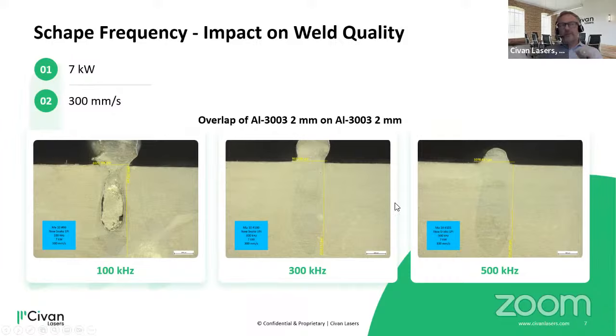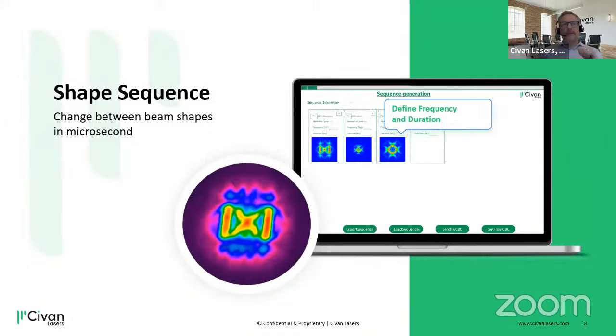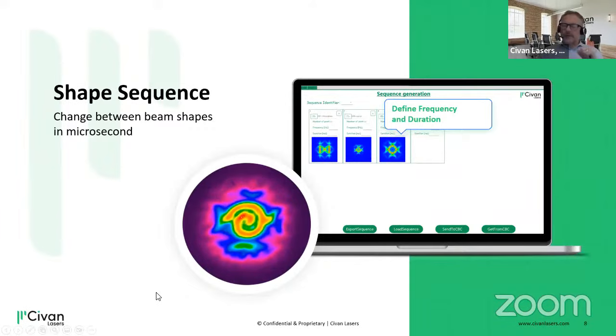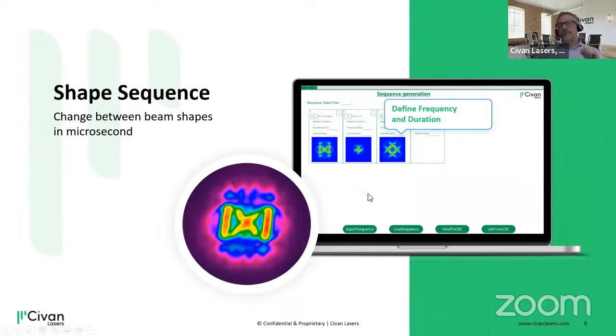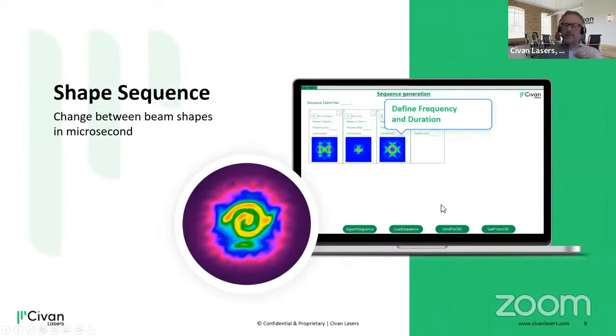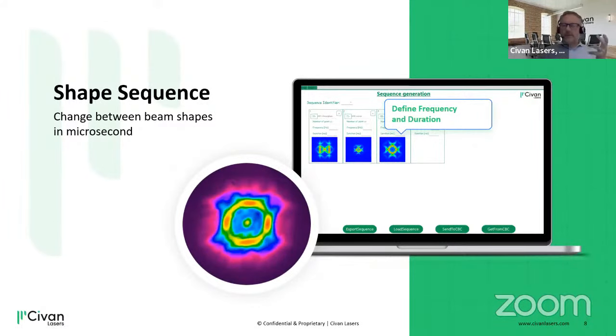So we have the shape and we have the frequency, both very relevant parameters that you can manipulate. And since, again, we're doing this at megahertz, we can create a series of different beam shapes addressing each individual problem. Because porosity typically is something where you want to steer the melt pool to keep the keyhole open.